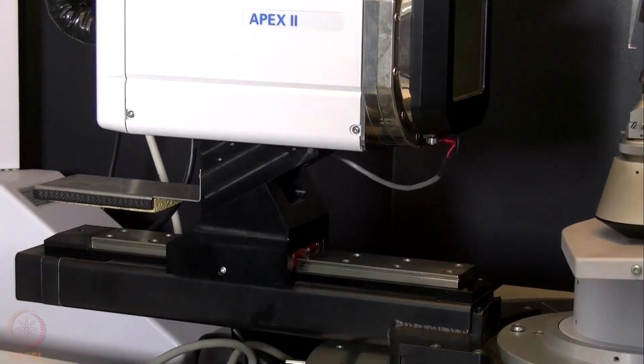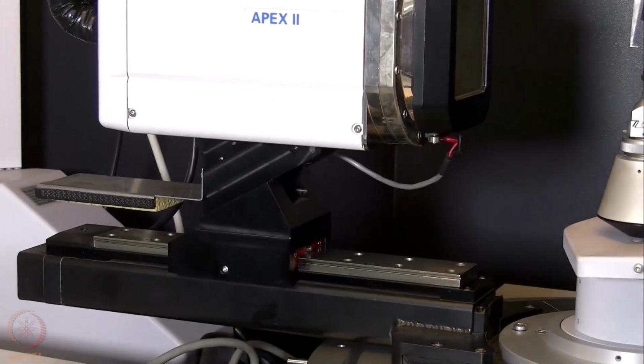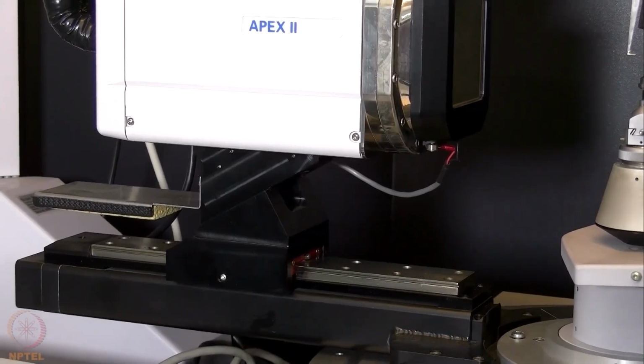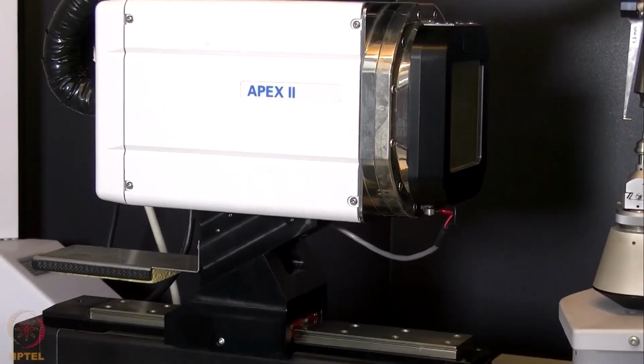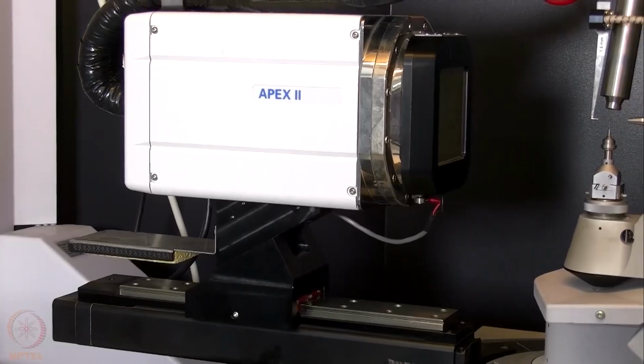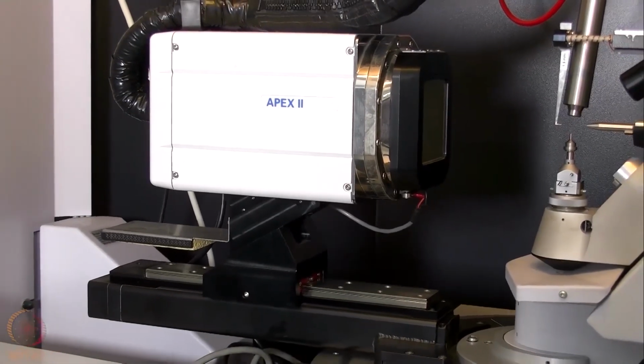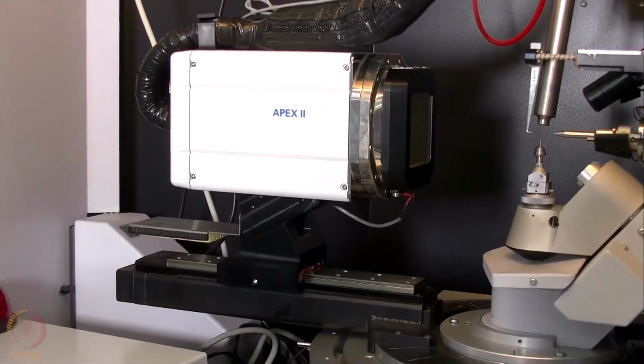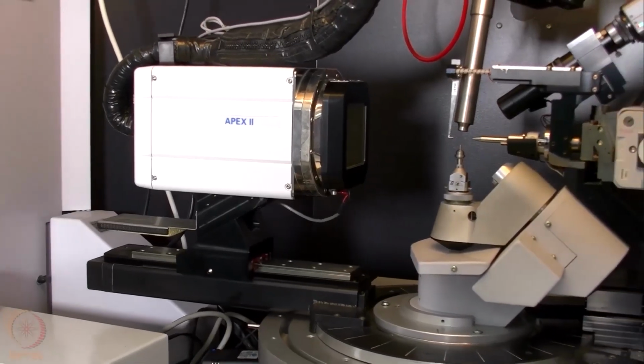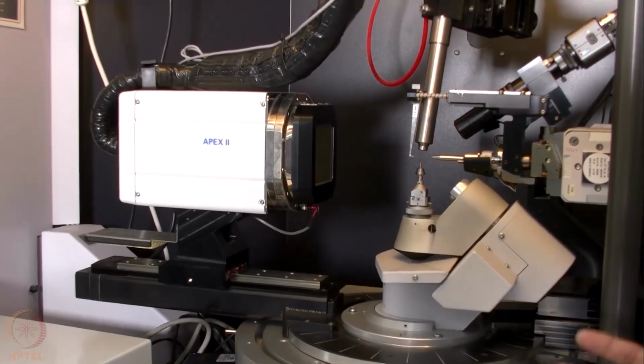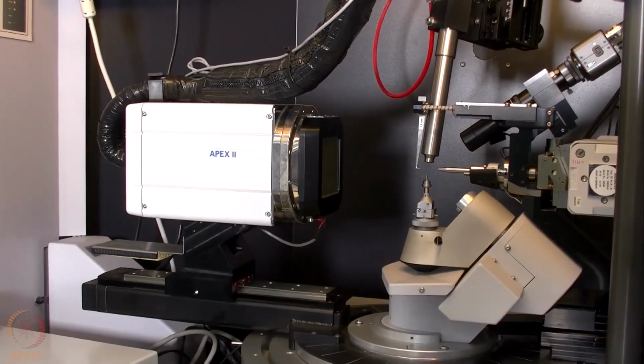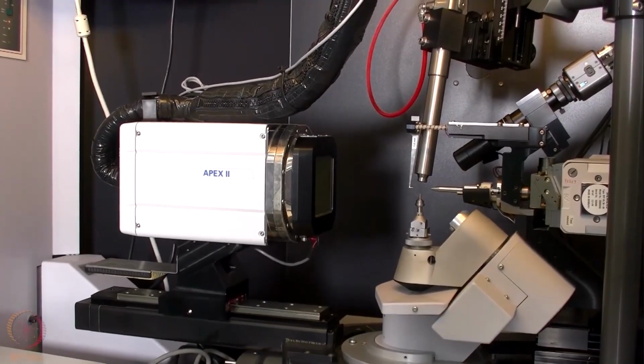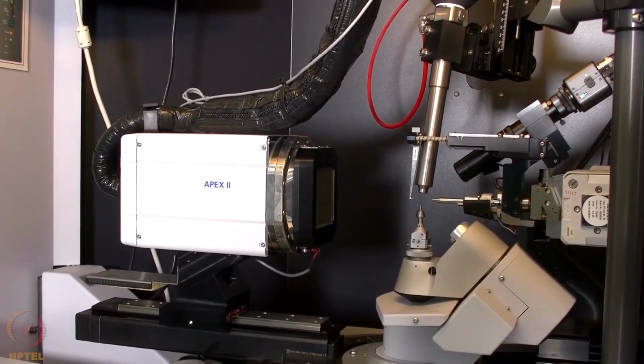So it makes it possible for us to record data with all 4 possible orientations of the 3 possible orientations of the crystal, and the detector is moved to a very high angle. So using this detector, one can record charge density quality data with a high angle position of the detector, like about 90 degree or 100 degree position of the detector.